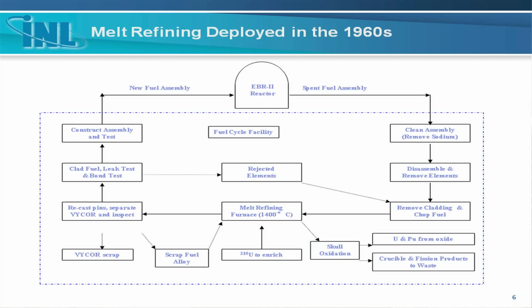Like I say, it showed that you could reprocess the fuel fairly simply. It was also able to show that you could refabricate the fuel fairly simply. They actually refabricated the fuel using an injection casting process. In addition to the co-location concept, that this fuel cycle facility was tied to the reactor, the one thing they were really able to demonstrate nicely is that they could take fuel from the reactor, reprocess it, remotely fabricate material from it, and get it back into the reactor in under 100 days, including all the cooling time. So they demonstrated that aspect of the dry processes.